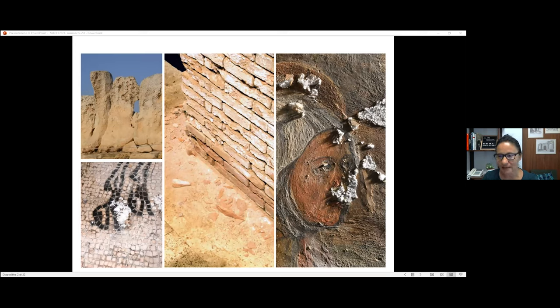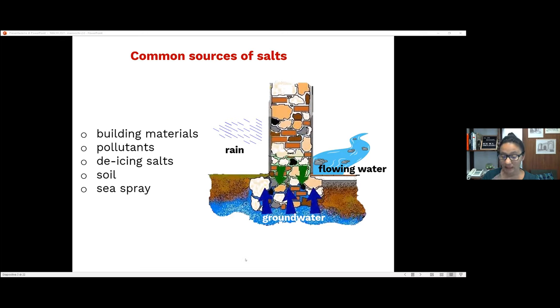I will go directly into the problem, that is salt crystallization damage, which is recognized as one of the major causes of material degradation, and it is particularly relevant in historical buildings and archaeological sites. Salt is present typically inside building stone as free ions. Let's talk about chloride, nitrate, sulfate, and so on. And it can be a natural element of the material. And it can be created, for example, by reaction with pollutants or introduced by water solution into the porous matrix by different processes. And the most important of these processes is undoubtedly the rising damp. And this is also the most difficult to remove when dealing with old buildings, actually.